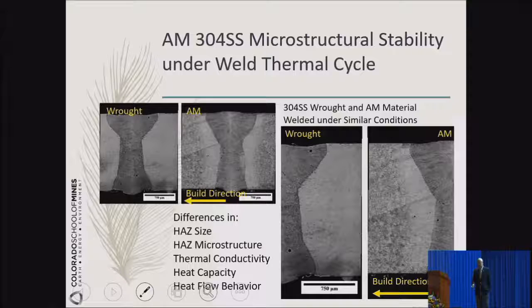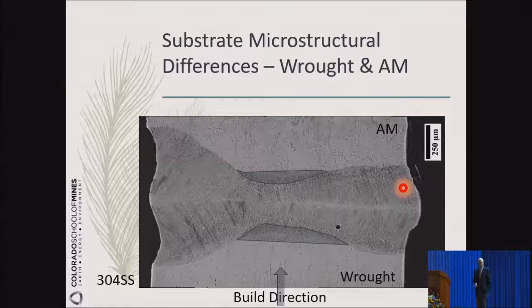So to further look at this here, just by enlarging the left-hand side diagrams here, you have the wrought material. You can hardly distinguish the heat affected zone behavior, the heat affected zone microstructure. But when you look at the AM material, look at how clearly the microstructure developed. So those are other things that we need to be careful in.